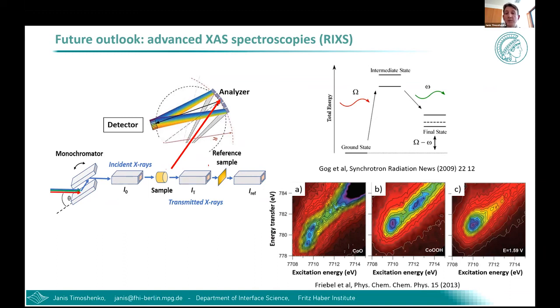crossover between X-ray absorption and X-ray emission spectroscopy, and is a very powerful approach to study in detail the electronic structure of the material and excitations in the material, and can be used, for example, to distinguish with much better accuracy between different species present under reaction conditions, or to study interactions between a metallic catalyst and the adsorbates.